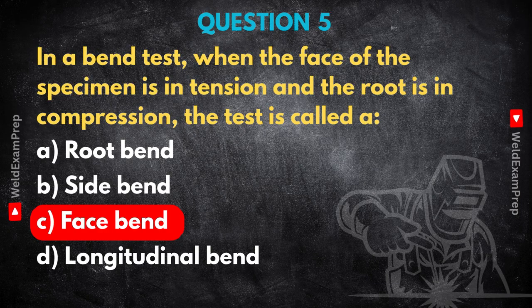At the same time, the root of the weld, the other side where the first pass went down, is on the inner curve of the bend. So the root is experiencing compressive stress. It's being pushed together. Now, this test setup is specifically designed to check the ductility, how much it can stretch without breaking, and the soundness of the weld metal, and also the heat-affected zone right there on the weld face under maximum tension. It's really good at revealing any surface or near-surface flaws. Things like porosity, lack of fusion, maybe some small inclusions, things you might miss visually.